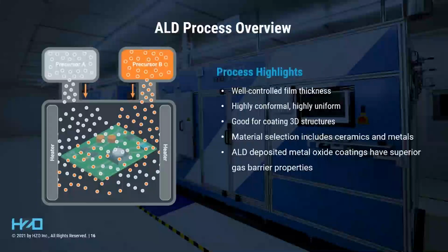The good thing about ALD is it's often effective in layers as thin as 100, 200 nanometers. So you don't have to run these cycles too many times to get to an effective film. The films are incredibly dense with some of the best gas barrier properties available. The chemistry is specific and slightly limited compared to plasma as far as the precursors go, but the options can be tailored to very specific properties.